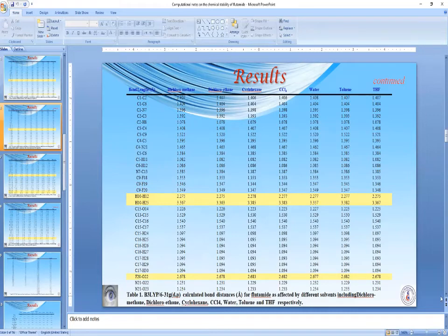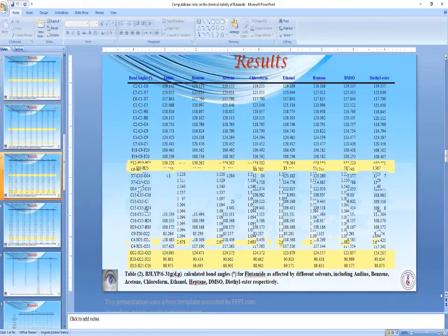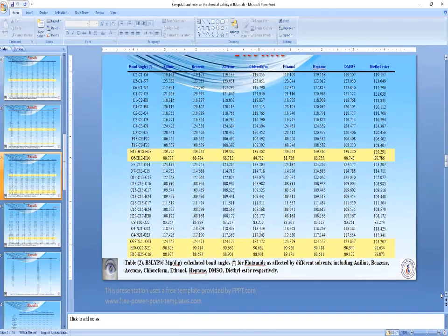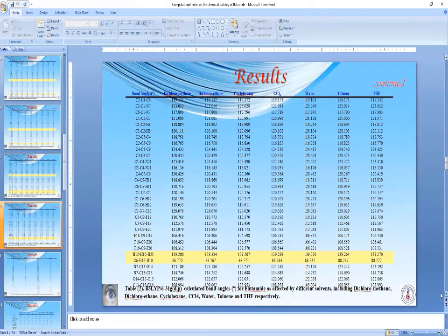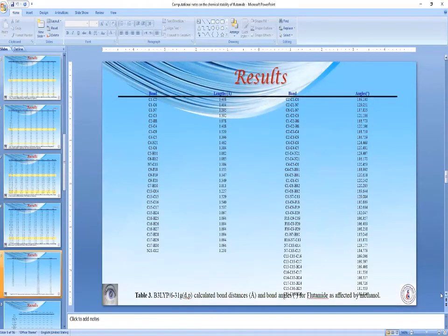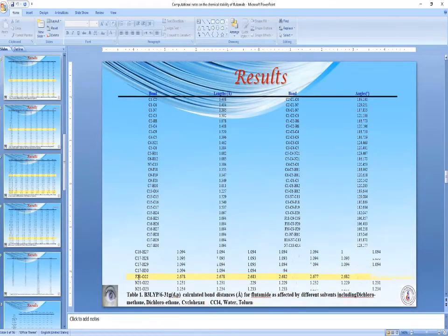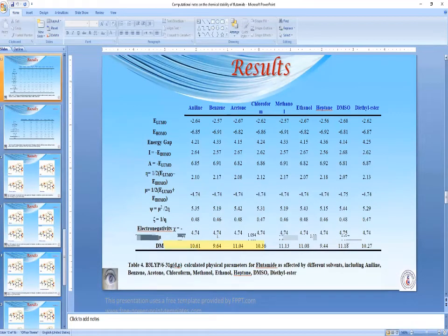On the contrary, for methanol, there is neither hydrogen bonding nor electrostatic interactions. Tables 4 and 5 show that the reactivity of flutamide varies up and down depending on the solvent. For example, the highest flutamide reactivity is in water, while the lowest is in heptane.